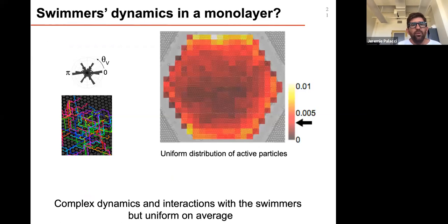Okay. So the next thing we did with the monolayer is to look at the average distribution of the statistic of the microswimmers in the crystal. The reason for that is that initially when we did the experiment, we looked at the trajectory of the microswimmers, and we decided to try to see how those microswimmers would interact with the grain boundary and the rest of the monolayer. But it ended up excruciatingly difficult because you would have to account for the inclination with the grain boundary, and it was very hard to repeat the experiment, and every grain boundary would interact with other grain boundaries. So it was just very difficult to get anything quantitative and reliable.